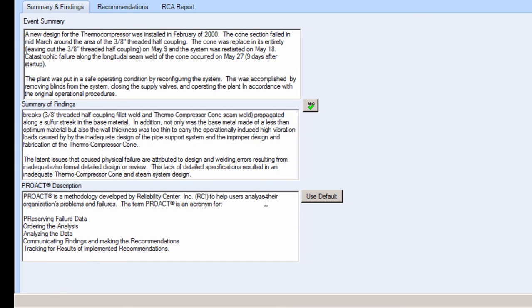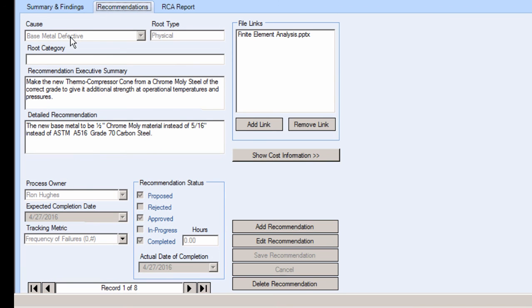The latent issues that cause physical failure are attributed to design and welding errors resulting from inadequate or no formal detailed design or review. The lack of detailed specifications resulted in an inadequate thermo-compressor cone and steam system design. So let's look at our recommendations here for our roots. So for example, this is a physical root cause, and I won't go into all the detail, I'll just give you an idea. The base metal is defective, that's a physical root, so we're going to make a new thermo-compressor cone from a chromoly steel of the correct grade and give it additional strength at operational temperatures and pressures. And this tells you what the new material should be.